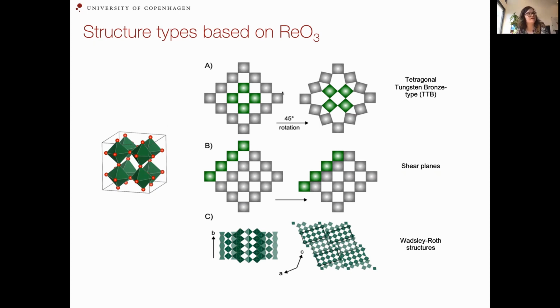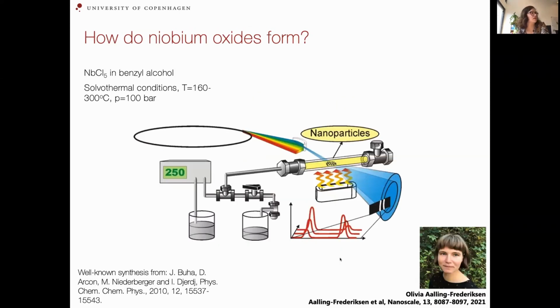Now if you take this structure, you can make different kinds of defects in it, and then you can get this tetragonal tungsten bronze type structure. Or you can shear, so you move some of these polyhedra, and you get shear planes. Or you can shear in 2 dimensions, and then you get Wadsley-Roth structures that are shown here. And niobium oxide forms especially these Wadsley-Roth structures, which we wanted to investigate.